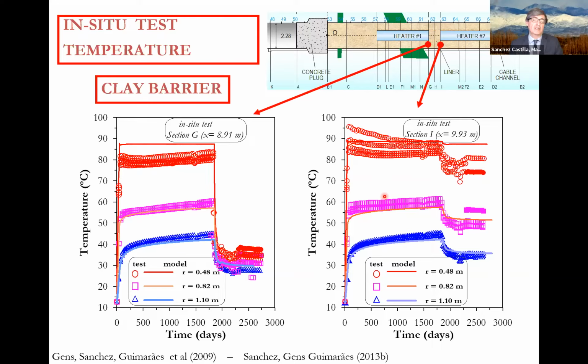So we provided the results, and what you can see here is the comparison between the model, with lines, and the experimental results in terms of temperature. This is what happened in different sections. This drop of temperature here is related to the switch off of heater one. So this is how the temperature evolved in different points. Close to the heater, we have the high temperature that we expect, about 80 to 90 degrees. Near the external part, at the contact with the gallery, it is around 40 Celsius, and in between at the central part of the gallery.